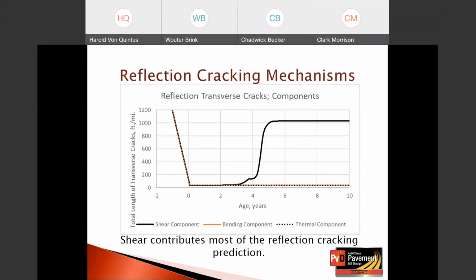This next slide shows the same thing, but for transverse cracks. It's a summary resulting in the same observation that we just made for fatigue. The shear, which is the solid black line, contributes most of the transverse reflective cracking prediction.